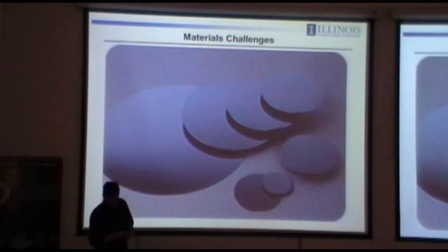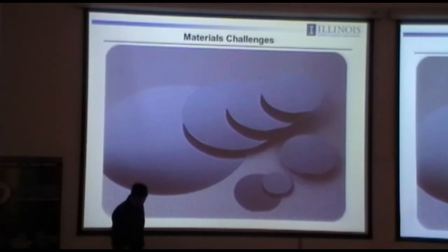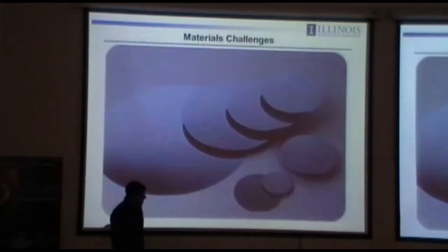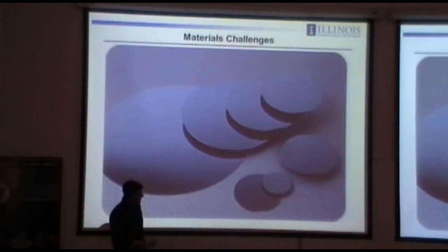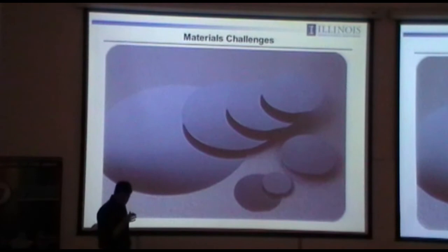Again, the starting point is the one that I mentioned several times already. Integrated circuits conventionally built on silicon wafers, millimeter thick, 150 gigapascal in modulus, 1% stretchability. And you know, if you look at that, you might think we really need to go to a completely different material because it's never going to work with silicon. Maybe you need to go to a polymer-based electronic system in order to get in this regime of mechanics. And that's certainly one direction that we've worked on, thinking about polymer small molecules. Joe Schoon, when he was in the group, were doing a lot with carbon nanotubes. I still think that that's an attractive approach as an alternative to silicon for these kind of bio-integrated systems.